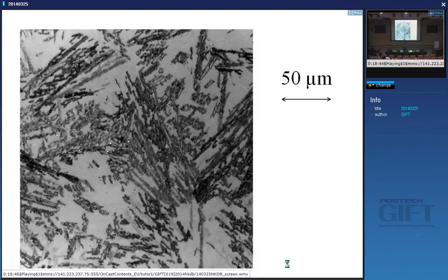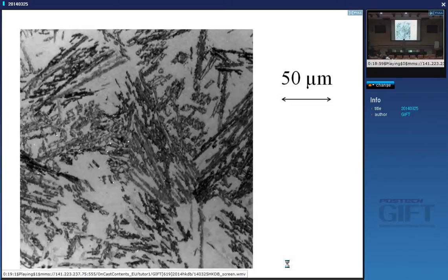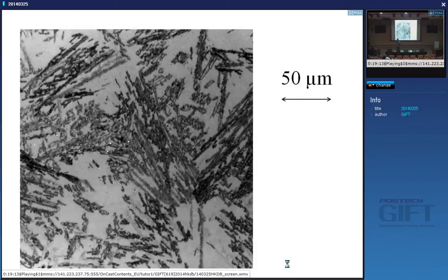The reason we have these large regions is the T0 curve — once the transformation reaches a point where the austenite has the same composition as the T0 curve, it stops. It doesn't matter if I hold it at temperature for a very long time, it will stop. So it seems there's nothing we can do about this because it's a thermodynamic limit. Let's see if we can play about with it — there are three ways.